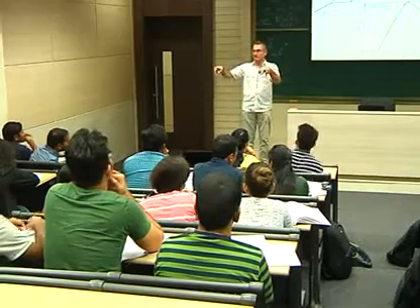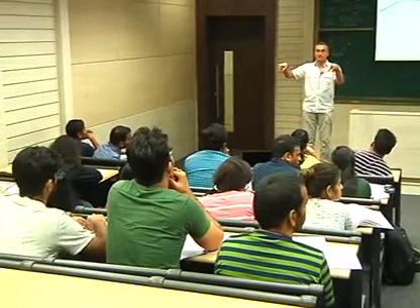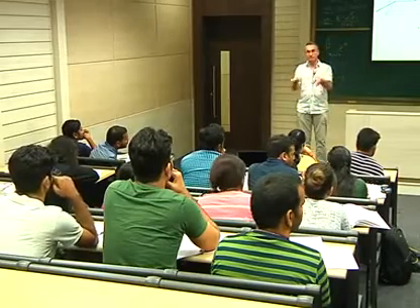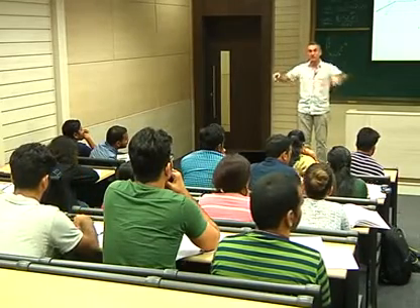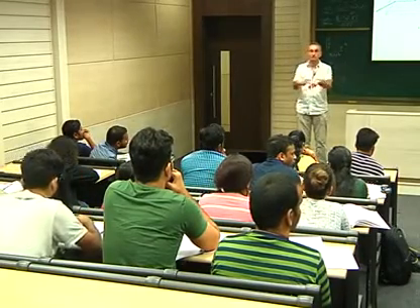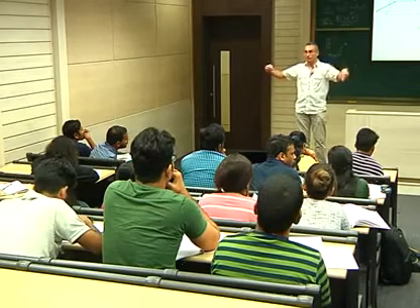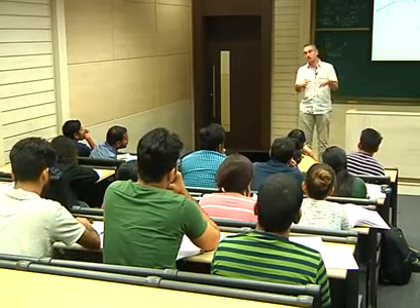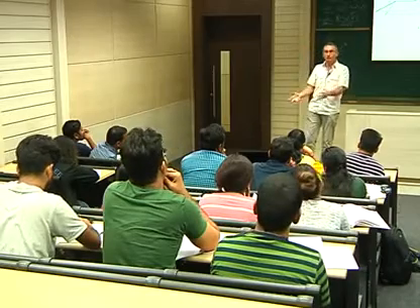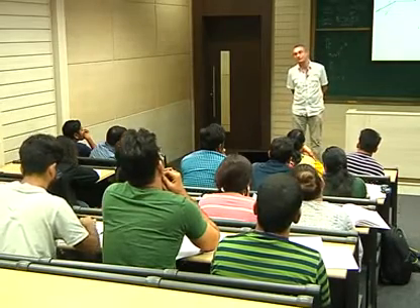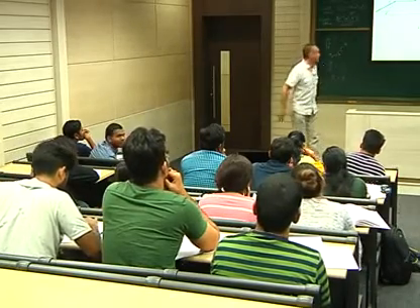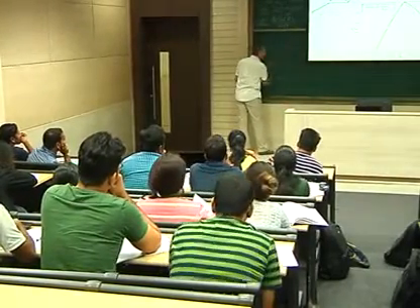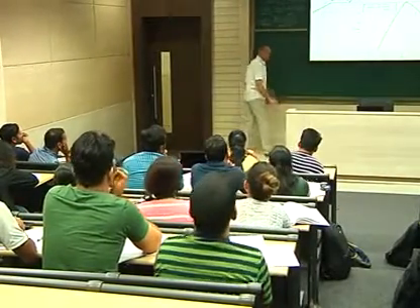The reason for that is that there is a very rare chance for the two dislocations to interact. You don't have many planes with many different dislocations. If they are in the same plane, usually they come from the same source. So it's not an interaction of two sources. If one source is going one way, the second source will go the same way. So it's not a junction. I would not call this a junction, maybe. It's not a hardening mechanism, at least. You see what I mean? I can make a picture maybe in 2D to explain why we don't say that this is a hardening mechanism.